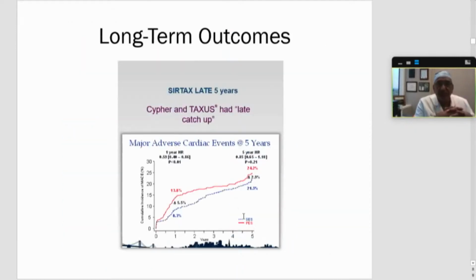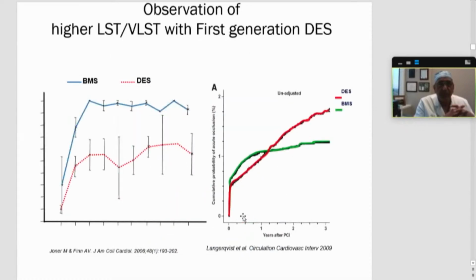However, there are some challenges with this first generation drug-eluting stent, namely late catch-up. So with Cypher and Taxus, both of them, we actually saw major adverse cardiac event rates at 5 years, amounting to 2 to 4% every year after that. So that was a little disappointing. And you can see that there was late stent thrombosis as well as very late stent thrombosis with these first generation drug-eluting stents, to the extent that it was slightly high with drug elution, and hence a concern sometimes about possibly moving back towards bare metal stents, which happened around 2008.